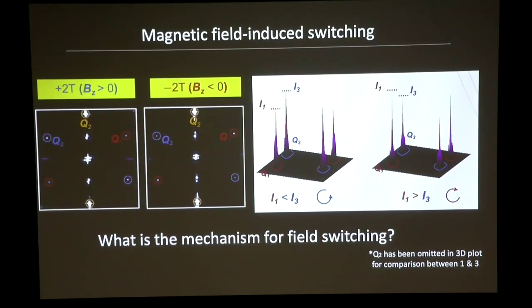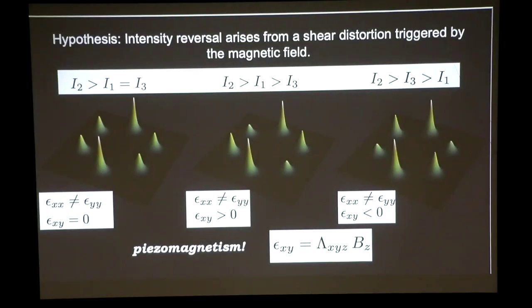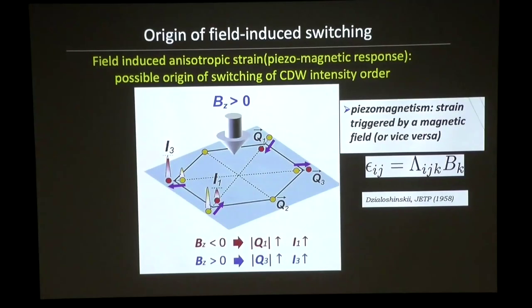And basically everything, just like light, every time you change the magnetic field, the charge density wave responds. Now, like I said, the mechanism behind this response is a very weird thing, right? How can a magnetic field in a perpendicular direction create a change in this charge density wave in plane? You can theorize that it's something called piezomagnetism, which is when you apply a magnetic field, the lattice actually distorts, just like we saw for light. So that would be the idea.